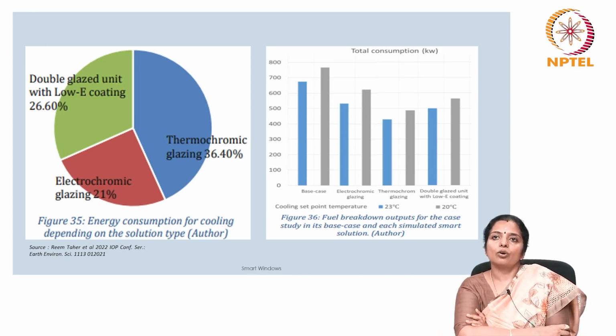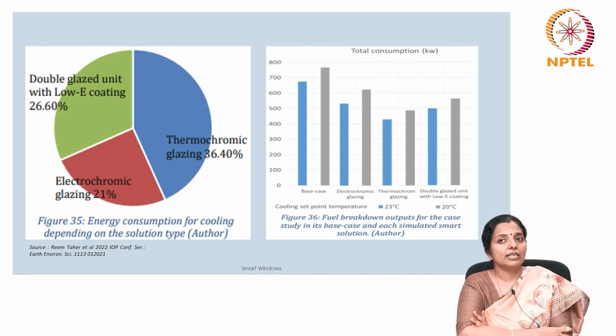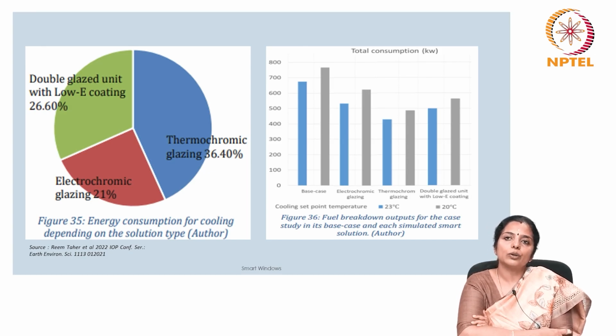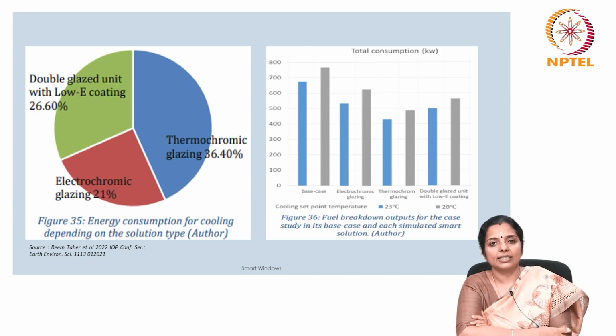From the analytical comparison of the outputs of simulating the building with the proposed smart solution and split air conditioning units, smart envelopes can reduce the energy consumption for cooling by about 21 to 36.4% depending on the solution type. Figure 36 summarizes the total fuel breakdown outputs for the case study in its base case in comparison to each simulated smart solution when the air conditioning unit set point temperature is set at 20 or 23 degrees centigrade. Energy consumption is reduced by about 12.5% to 14.5% when the set point temperature of the split unit is changed from 20 to 23 degrees centigrade.